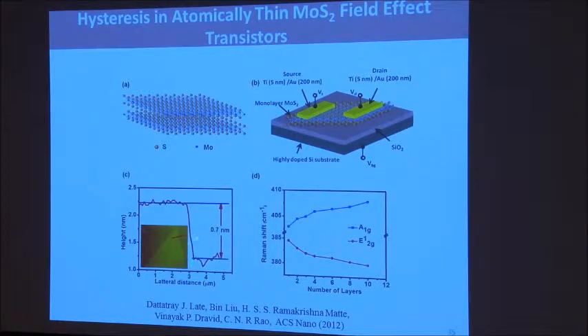You know what you have done by doing atomic force microscopy. You can see the thickness of this layer is exactly 0.7 nanometers, meaning it's a single-layer molybdenum sulfide I've used there. And then you can study the transistor properties of this material.